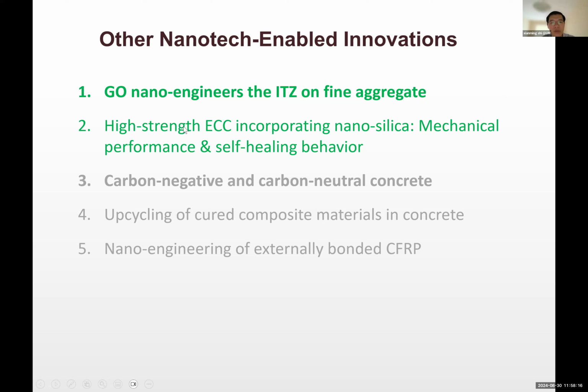And then another one is high strength ECC, or engineered cementitious composite, also known as bendable concrete. In this case, we incorporate nanosilica to enable better self-healing behavior because we keep the cracks really, really fine, less than 30 microns in width typically. And then, of course, other nanotechnologies like carbon negative concrete, we started this line of research.